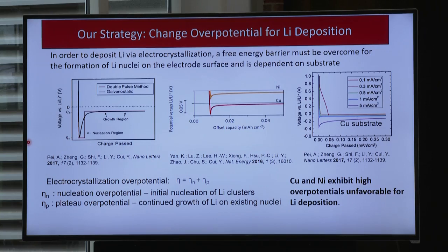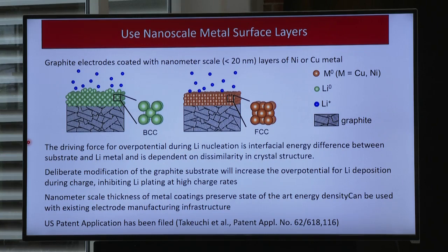So that's what we set out to do. And we studied what materials have unfavorable deposition for lithium. It turns out that certain metals, for example, copper and nickel, have unfavorable deposition, and we believe it's because there's a mismatch in the crystal structure of lithium versus the metal crystal structure. So this means that there's an energy barrier, a kinetic barrier, to trying to deposit lithium.